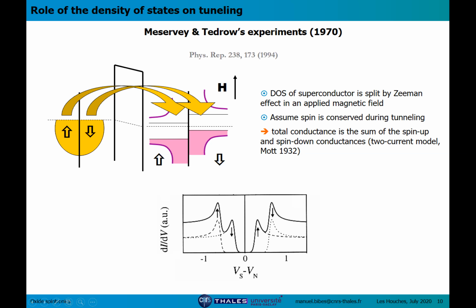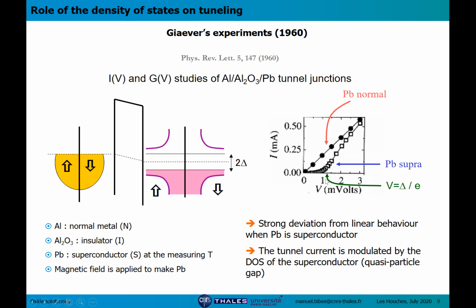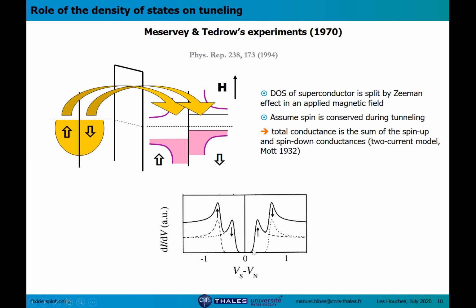So effectively, if you now measure the conductance as a function of the bias voltage, when the magnetic field is present, you're going to see this kind of curves. Basically, you're going to measure 4 peaks, and each peak corresponds to the onset of a finite current, similar to what I was showing you. So here you would have 1 peak, and you have a symmetric peak if you were to do the experiment at negative bias voltage. But now, because you have a magnetic field applied, you are seeing 2 gaps, 1 gap for spin down and 1 gap for spin up. So you have 2 peaks for positive bias and 2 peaks for negative bias.